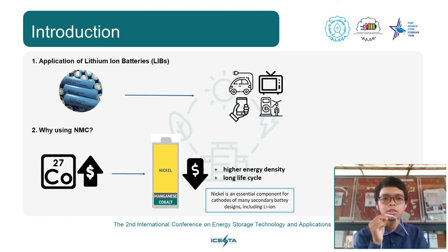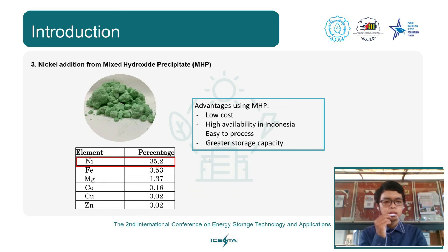In this research, we synthesize NMC in mole ratio 5:3:2. We use mixed hydroxide precipitate as nickel source to produce NMC cathode materials. Mixed hydroxide precipitate contains 35.2% of nickel, which is higher than the other components. However, the impurities can be used as doping for NMC cathode material. Mixed hydroxide precipitate has advantages such as reducing the cost, being easy to process, having greater storage capacity, and high availability in Indonesia.